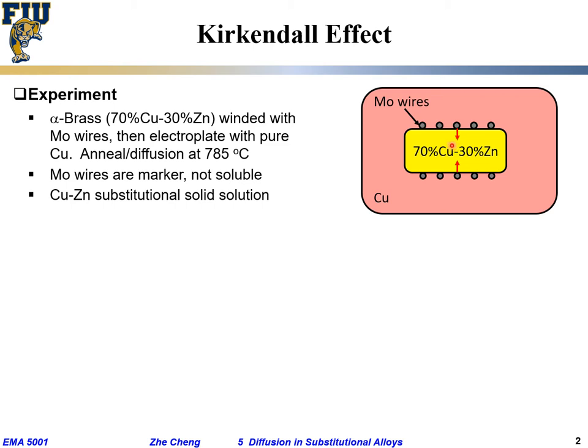They used pure copper — shown in pink — and so-called brass, shown in yellow. What is brass? It's 70% copper and 30% zinc — a single-phase solid solution alloy sitting in a single-phase region. The yellow piece is brass. Your typical key is not pure copper; keys are typically made of brass, as are many locks, because brass offers slightly better hardness and corrosion resistance compared to pure copper.